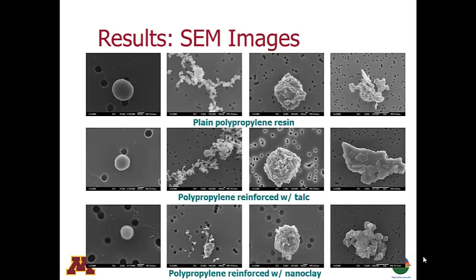Scanning electron microscope images of samples collected using the MOUDI impactor show that similar particles were captured from each of the three resins as they were shredded. Individual spherical particles may be a result of volatilization of the polymer as it is heated by shredding, followed by immediate recondensation in the surrounding air. We also see chain aggregates of spheres, as well as compact and more spread out agglomerates of smaller particles.